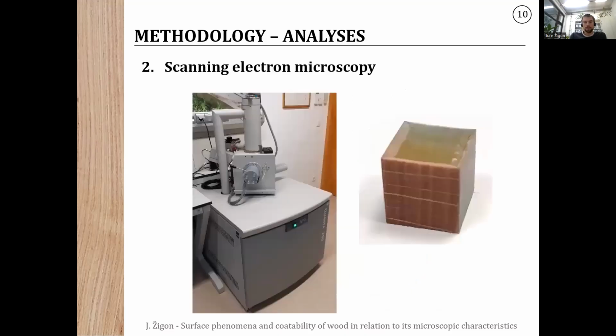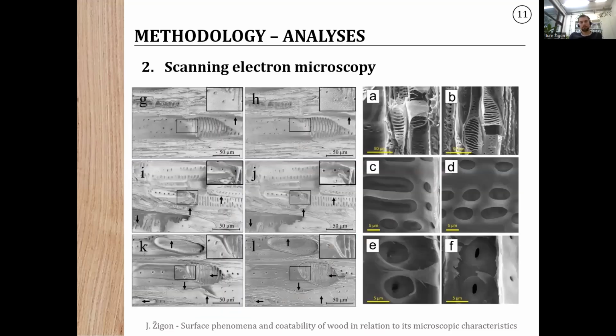influences. Another technique is scanning electron microscopy, which we do have at our department. We see the photo here, and one photo of the sample which was used, I think, for determination of penetration depth and the coating thickness. The sample must be properly prepared, as I said before, on the sliding microtome, and also sputtered with gold for better conductivity.